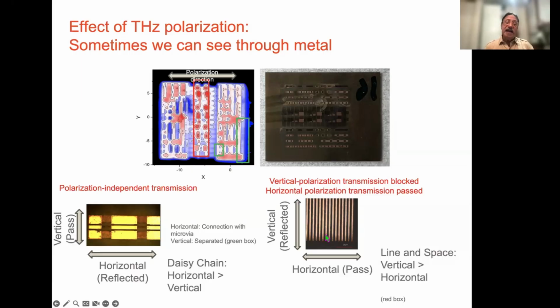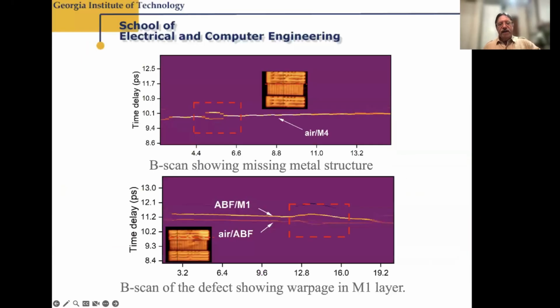We understand that it's basically a plasmon-polariton effect, that there's a different screening of the incident terahertz field depending upon the polarization that accounts for this effect. So it means that we actually can see through some metallization. Not all; we can't see through the daisy chain, but through these lines. And we can detect certain kinds of defects in this structure.